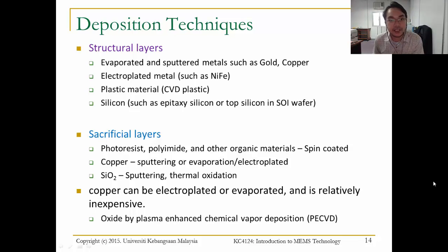Now let's look at the deposition techniques available for us to deposit structural or sacrificial layers. Regardless of whether we are depositing structural or sacrificial layers, the type of the layer will determine what deposition technique we have to use. For example, for metal-based materials or layers, we can use either evaporation, sputtering, or electroplating. For plastic material or non-metals, we can use CVD. For silicon-based structural layers, we can use molecular beam epitaxy. For silicon dioxide in sacrificial layer, we can use either sputtering or thermal oxidation.